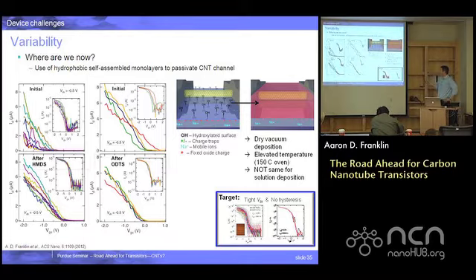And what was amazing is putting this sort of a crude layer down did a miraculous job of pushing these curves together. They're still not perfect, but just by passivating, these same devices before and after tighten considerably. This tells us that a lot of that variation that's present is caused by the interaction between the nanotube and all the stuff that's happening on the surface around it. So protecting them in the proper way is a very important step to having the path towards getting a transistor that makes technological sense.